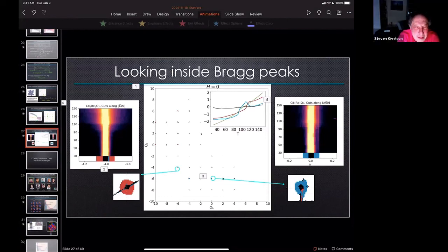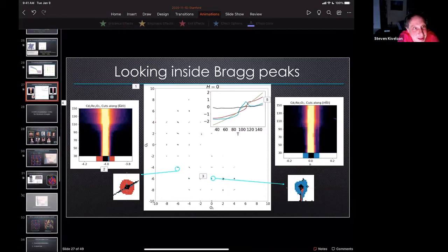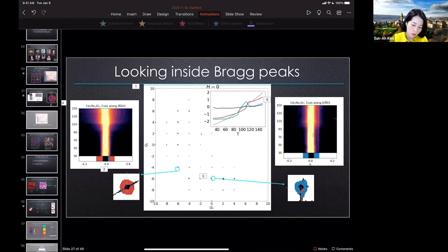Okay, and then I'm even more confused about the second half. I didn't understand what the question was. I think there's a sharp question about what the symmetry is. So the question was, you have this data, you have these snapshots, and you want to figure out which model or which idea gets closest to the data. But what does that mean? This is hypothesis testing. It's the same kind of line as when we look at STM data of a disordered charge density wave. I want to see whether my disordered charge density wave looks more like disorder from a commensurate or from an incommensurate charge density wave.